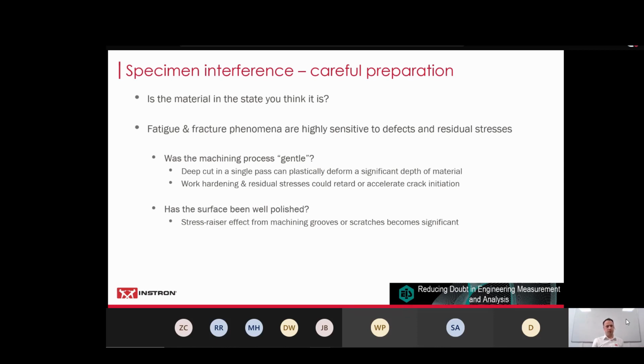On a similar topic, I mentioned final cut and polishing. You look at international standards on fatigue testing, they mention certain levels of surface finish on the specimen. So we do need to get down below a certain effect. Unless, caveat on this, you are going to do a test on a specimen where you're interested in the surface finish and you want it to be representative of some part. And there we're starting to diverge from materials testing, and we're starting to understand a little bit more about simulating the real parts. But make sure it's not having an inappropriate effect.